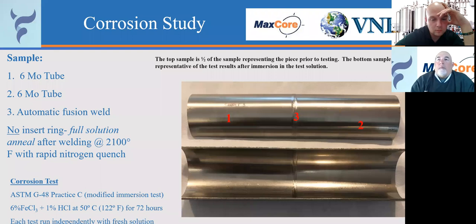This is another sample of a 6-moly tube welded to a 6-moly tube identical to the first weld that we did. In this particular case, we did not use a weld insert ring, but what we did do was a full solution anneal on the product. So we did that after we did the welding at 2100 degrees Fahrenheit, followed by a rapid nitrogen quench. Now, in this particular case, there was no corrosion that took place in this particular area. What this does, by doing an annealing process, is it rehomogenizes that weld area and distributes those properties throughout that metal again, giving that corrosion resistance similar to the base metal back across the weld.